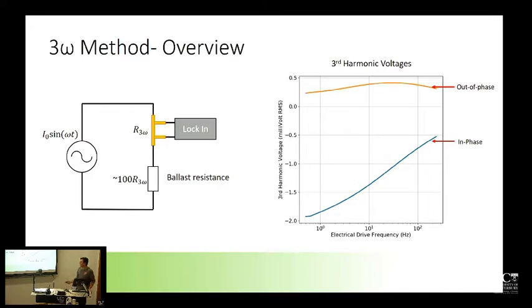So in the thermal conductivity experiment, what you do is you provide a sinusoidal current through it with some large ballast resistance, which is more than 100 times what your actual thermometer resistance is. And then you monitor the third harmonic, which is linearly dependent on the temperature of the line. And what you find is that as you increase your electrical driving frequency, you get a decrease in the temperature response of the system. So essentially what you're measuring here is a transfer function where your input is heat energy into the system and your output is temperature.